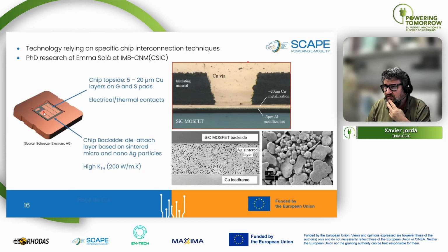And we need also a very good die attach layer. This means the layer which fixes the die, the chip of the MOSFET, to this copper lead frame. And in our case, we have used micron and nanoparticles, silver micron and nanoparticles, which have been sintered. This layer, this is the final layer that is achieved using this approach, shows very good thermal and electrical conductivities.